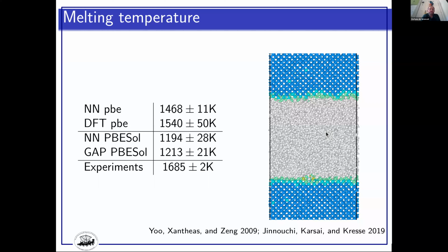There are in the literature DFT results for the PBE melting temperature, and it is 1540, which is within error bars. They are the same, so they are compatible with each other. So our neural network really seems to model well the PBE potential.